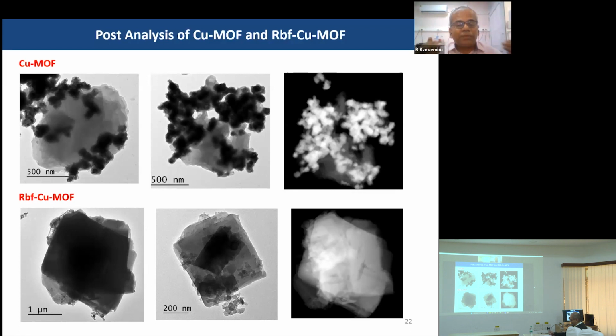So even after many cycles and long duration of catalysis, we observed no change in the structure of the copper MOF once riboflavin is introduced into it. This might be one of the reasons for the enhanced activity of the riboflavin modified copper MOF in the reduction of carbon dioxide into formic acid.